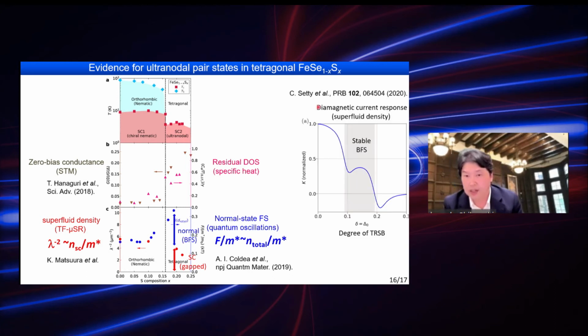Moreover, the theoretical group has calculated the diamagnetic current response, which is related to the superfluid density, in the calculation parameter range. They found that within the parameter range in which the Bogoliubov Fermi surface becomes stable, shown by this gray shade, the superfluid density shows a substantial decrease from the original value, which is consistent with our transverse field μSR measurement data.